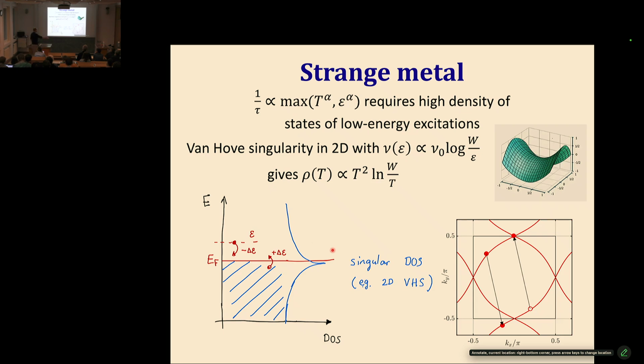And here this point that was mentioned before comes in a very important way. If you calculate the scattering rate of a single electron close to the Fermi surface, as opposed to the scattering rate of the electrical current, you'll get parametrically different results in this example. The electrical resistivity turns out to be T squared times this logarithmic correction, log of the bandwidth divided by temperature. If you calculate the scattering rate of a single electron, that actually follows a power law, T to the power 3/2. So it's a non-Fermi liquid power law, which doesn't show up in the resistivity. There is a violation of the T squared law, but it's not by power law, it's only by log. And can this actually be done?